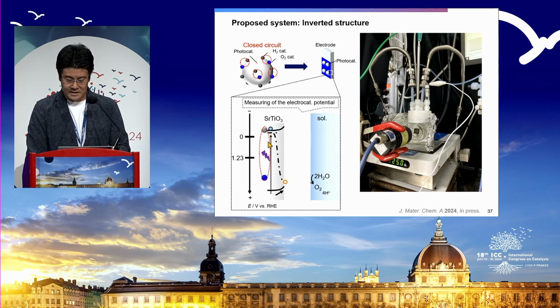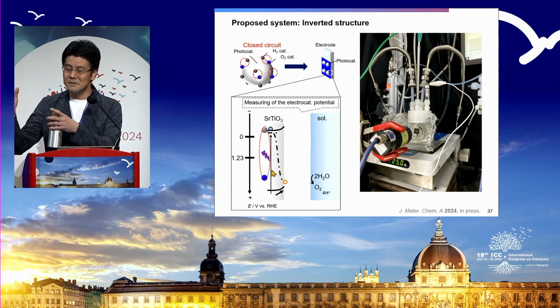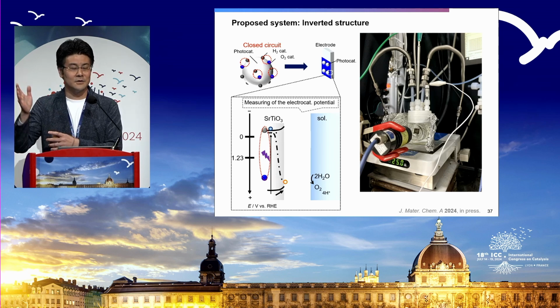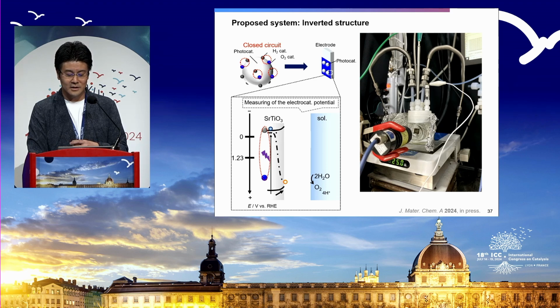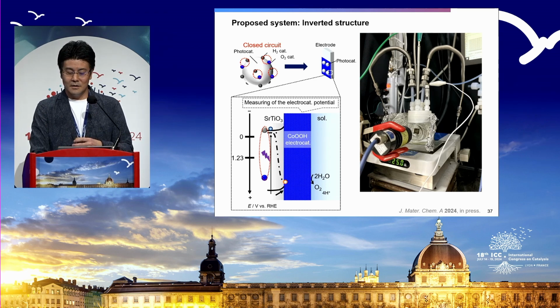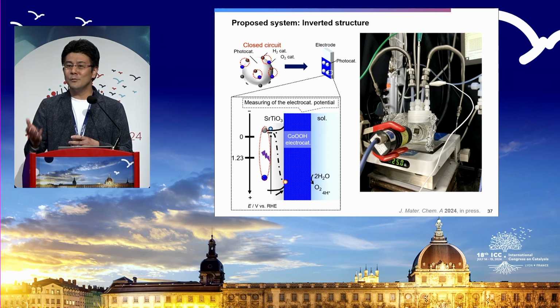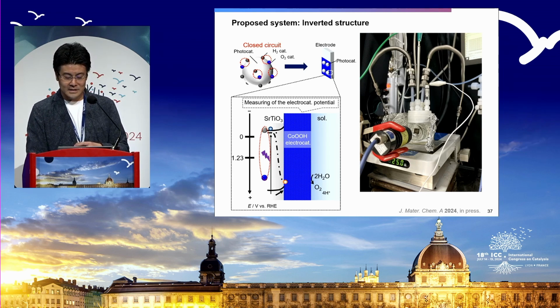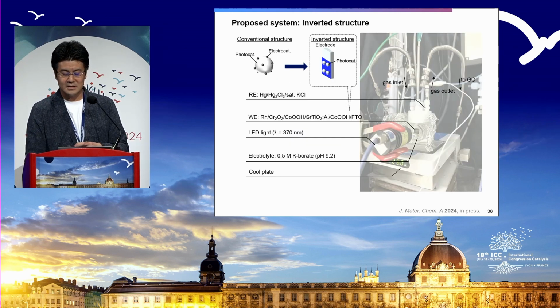So basically, like I said, in this scheme, you can confirm that hydrogen and oxygen are a closed circuit. You already do it in a good way, right? If the rate of hydrogen and oxygen evolution is in a 2-to-1 ratio, actually, you don't need extra here. But what we are trying to do is put this one, hopefully with part of the holes going to this cobalt electrode. Just to show that this is a typical 3-electrode system that we are using.